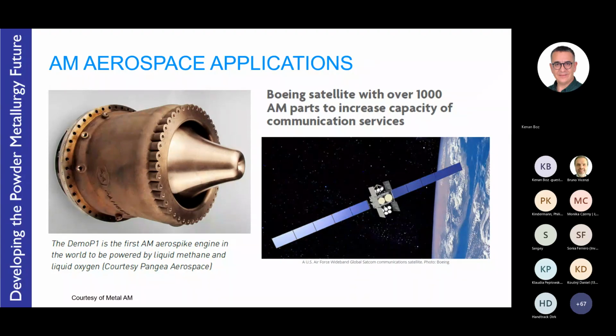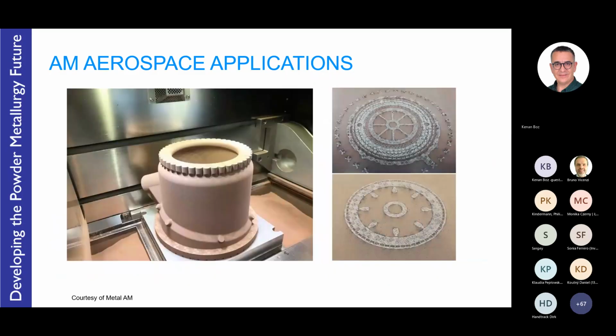So it's a development from the 1950s, and it has found renewed interest because at the time in the 50s, they couldn't really produce it economically enough. But with the advent of additive manufacturing and printing processes, with being able to incorporate the cooling channels and the complex internal structures, this type of rocket nozzle has found a new lease of life. And also the materials applied. You see, it's a copper color, typically a copper chrome zirconium or a copper chrome niobium.